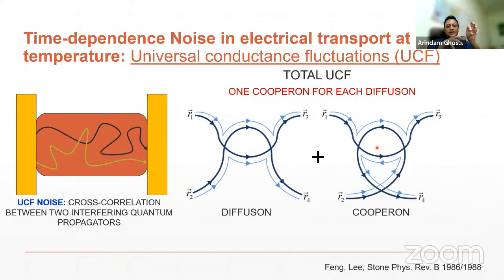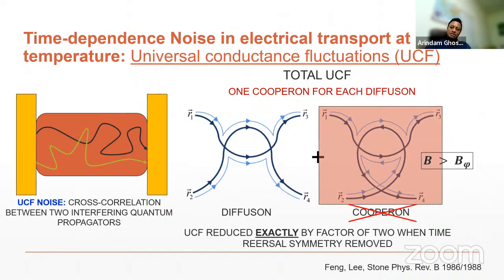Okay. So that means that if I apply now a magnetic field here, then the path in which they are moving in opposite direction, they accumulate random phases in the sample and they get averaged out. So there are two possibilities, out of which one possibility vanishes. So what happens because of that, the total noise in the system comes down by a factor of two. So UCF is reduced exactly by a factor of two when the time reversal symmetry is removed.